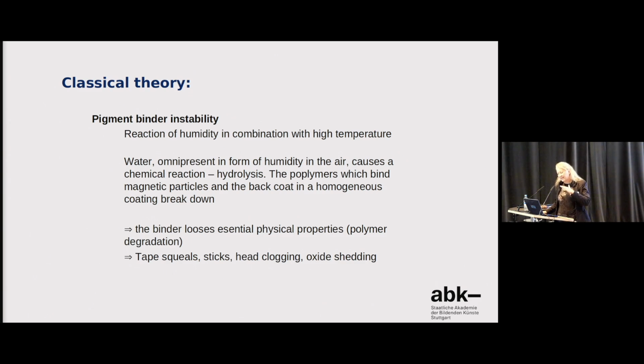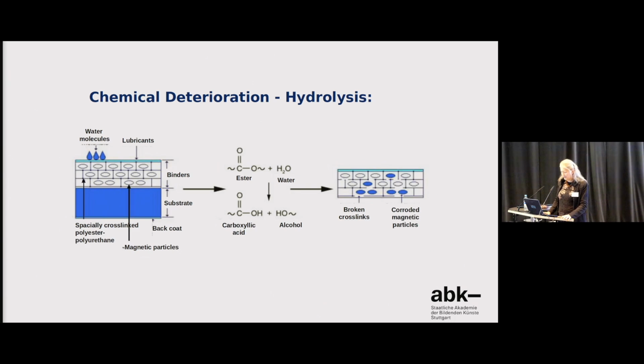The classical theory is the classical hydrolysis reaction. Pigment binder instability is a reaction of humidity in combination with high temperature. So water, which is omnipresent in form of humidity in the air, causes a chemical reaction which is called hydrolysis. The polymers which bind magnetic particles and the backcoat in a homogeneous coating break down. The binder loses essential physical properties, and the tape starts squealing, sticking, head clogging, oxide shedding. Here is a schema of this reaction.